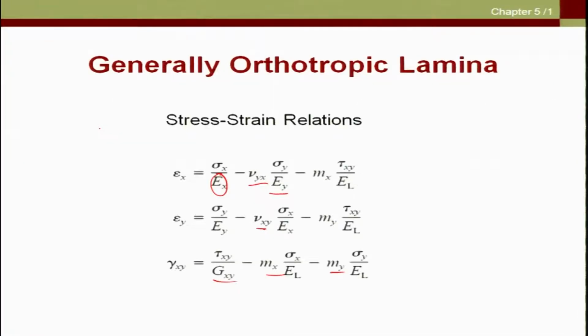So, this is consistent with our original stress strain relations, because here what we see is that when theta equals 0 or theta equals 90 degrees, our axis system will be aligned with the material axis of the system. That is, we will not have the generally orthotropic lamina situation, rather that will simplify into the especially orthotropic lamina situation, and in that case when we have